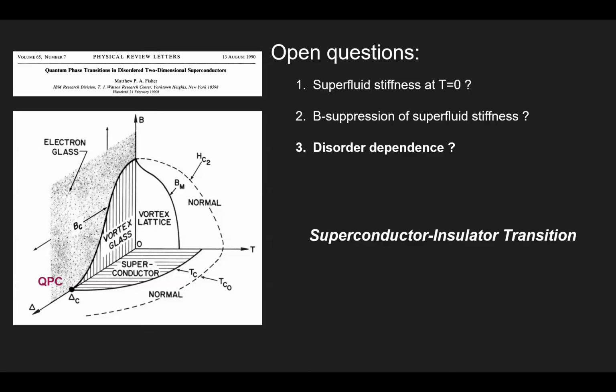So I just remind you what the superconductor-insulator transition is, which is pictured by this iconic phase diagram proposed by Matthew Fisher quite some time ago, in 1990. This is the basic phase diagram of a 2D superconductor. You have temperature, magnetic field, and this delta here is disorder. It's not the gap, so it's a bit confusing, but that's how it is. And you recognize in the temperature-disorder plane the standard decrease of Tc with disorder, and because it's 2D, you have a Berezinskii-Kosterlitz-Thouless transition, whatever. And you have a quantum critical point where superconductivity is destroyed.